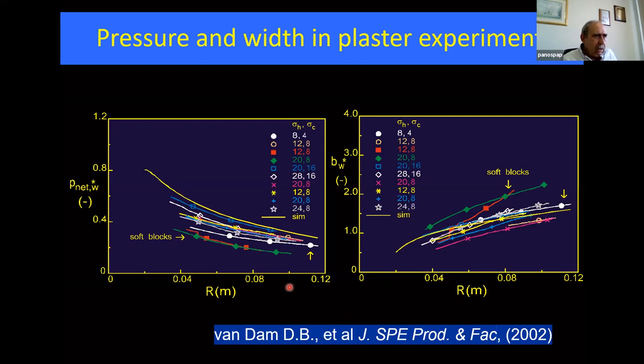Actually, yes, this is some of the results for the net pressure as the fracture propagates, and for the fracture width as the fracture propagates. The net pressures are quite close, and even for soft blocks, it's lower. And the reason, as I show in the results, is that when the fracture is wider, the fluid front reaches closer to the tip, and back at the bottom it could be very close or even lower, as it shows here. But here you can see clearly that the fractures in the soft blocks are much wider.